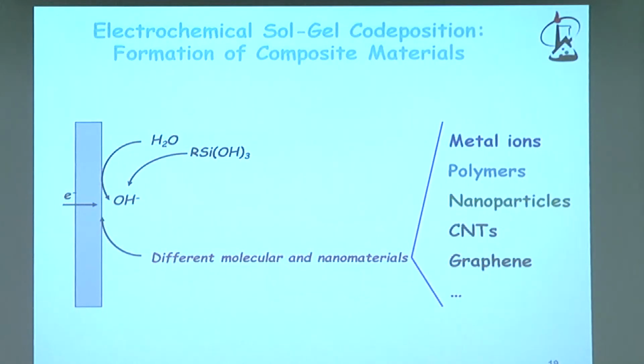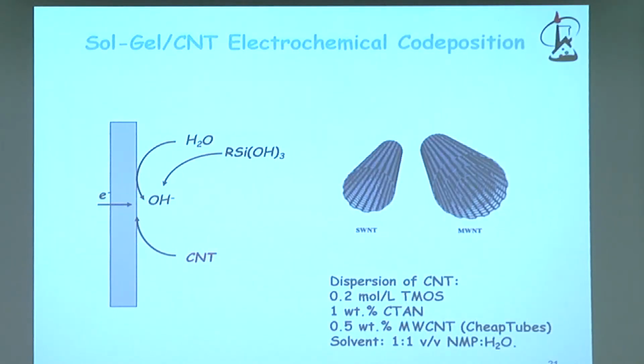You can also add to the sol-gel different materials, such as carbon nanotubes, graphene, nanoparticles, and so on, providing that they interact somehow with the monomer. And because of that, you get co-deposition. So the sol-gel, once it deposits, it takes with it the different materials you add to the solution. And again, I'll give you only one example, and this is with carbon nanotubes.